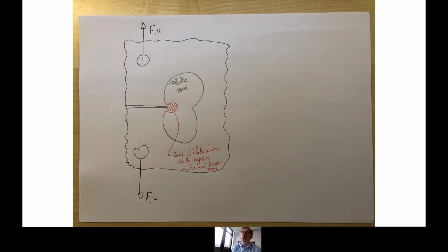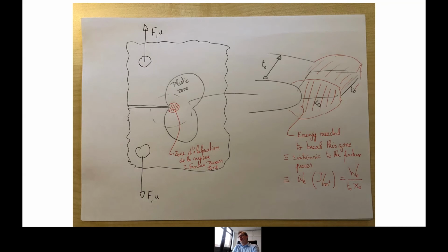It is the volume of material in which the failure process, the plasticity, the damage and failure, will localize. So it's a zone of finite dimension, and its dimension will scale with a length which I will call x0. More important is also the thickness of that zone, which I will also call x0. I will assume this zone is more or less equiaxed, which is not completely true, but the fracture process zone is really where the failure process takes place, and it is the zone in which the fracture energy will be dictated. And T0 is what I will use as the thickness of the specimen.